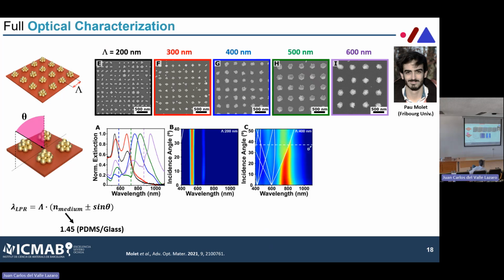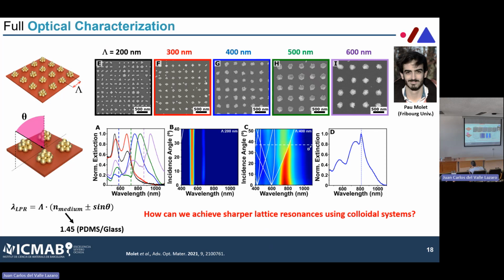And so what we started to observe is that if we look at the diffraction line, there is a specific angle where the diffraction line crosses the response. So in those conditions, you start to see very sharp features. However, this is not optimal. What you're seeing here is that this blue line is not the lattice resonance, but the response of these clusters over here. Overimposed on that, there is our lattice resonance that appears at a certain angle. And so we start again asking the same question that motivated us, which is how can we achieve sharp lattice resonances?